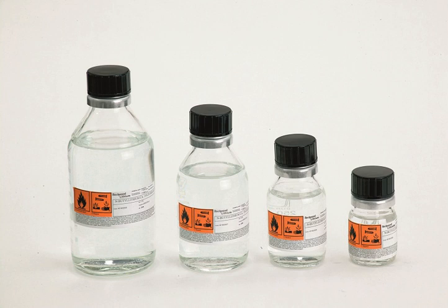Organolithium reagents are also better than Grignard reagents in their ability to react with carboxylic acids to form ketones. This reaction can be optimized by carefully controlling the amount of organolithium reagent added, or using trimethylsilyl chloride to quench excess lithium reagent. A more common way to synthesize ketones is through the addition of organolithium reagents to Weinreb amides, N-methoxy-N-methyl amides. This reaction provides ketones even when the organolithium reagent is used in excess, due to chelation of the lithium ion between the N-methoxy oxygen and the carbonyl oxygen, which forms a tetrahedral intermediate that collapses upon acidic workup.